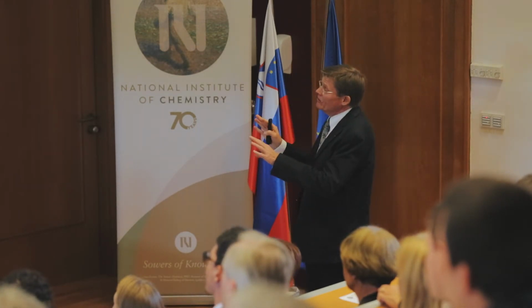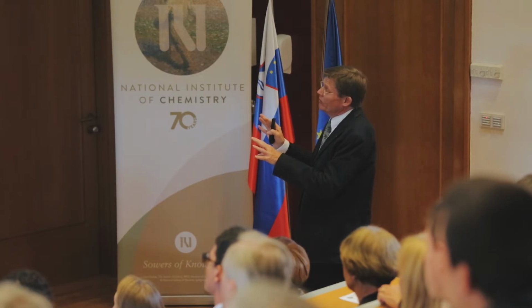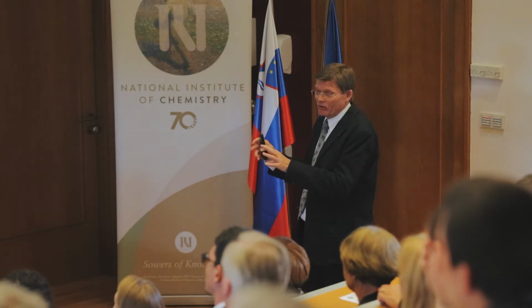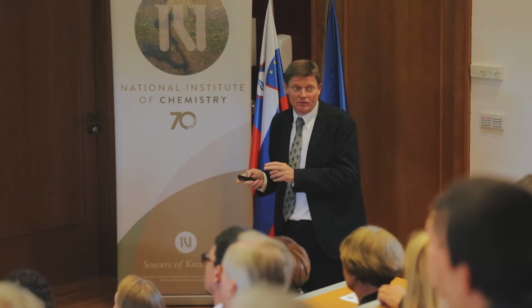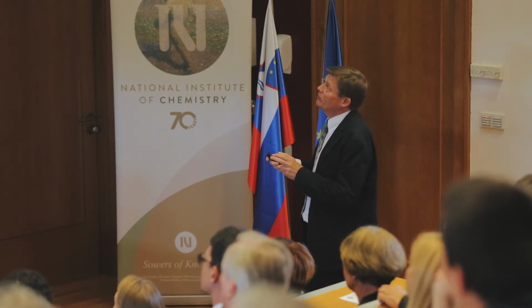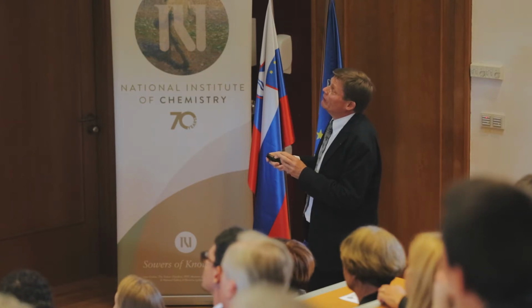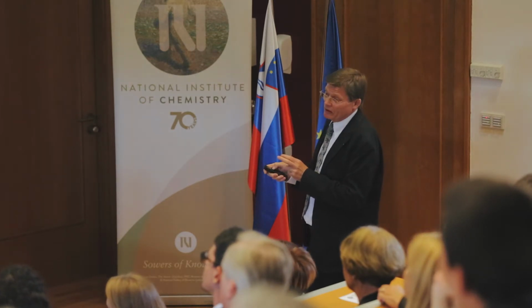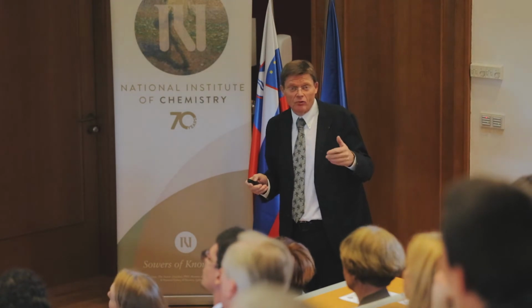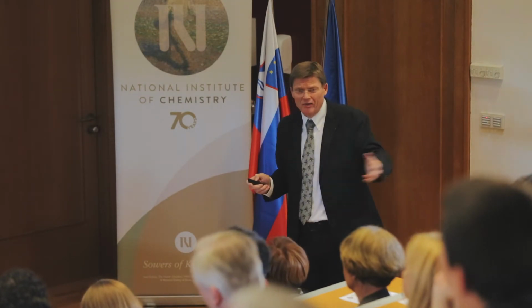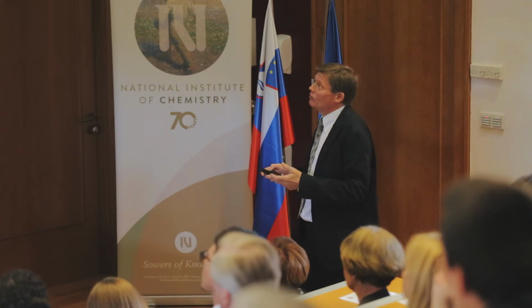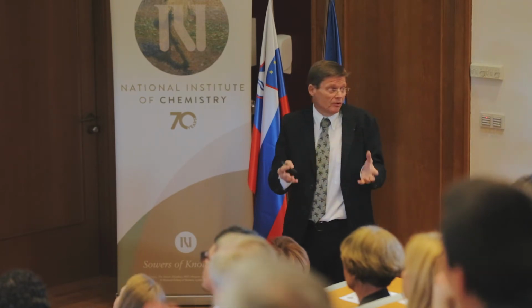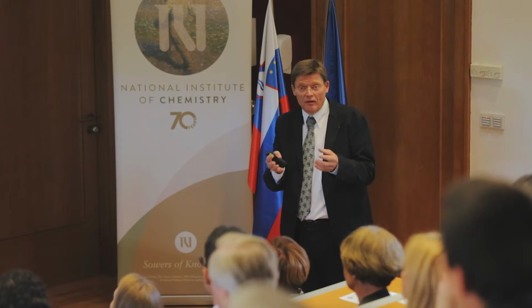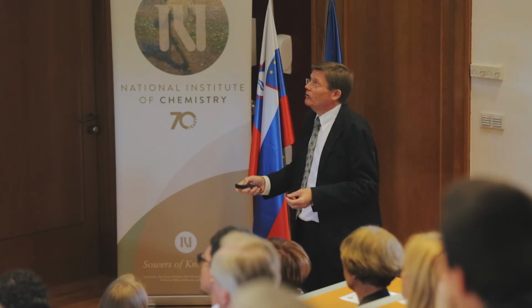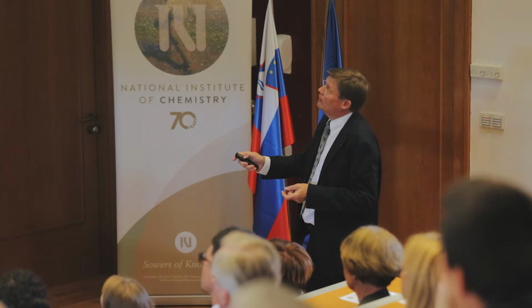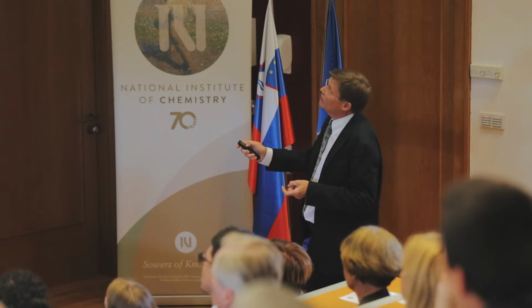As nice as these things look, they are not very satisfactory. Everything is extremely sluggish because lithium oxide is a very, very bad conductor. So then, recently, this is my last example, we went to a material which is very well conducting, which is silver iodide. This is a so-called super ion conductor. Silver ions are extremely well conducting, and graphite is a good electron conductor. So we made a composite. You cannot store silver in any of these materials separately, so you put them together. And then you can store it like that.